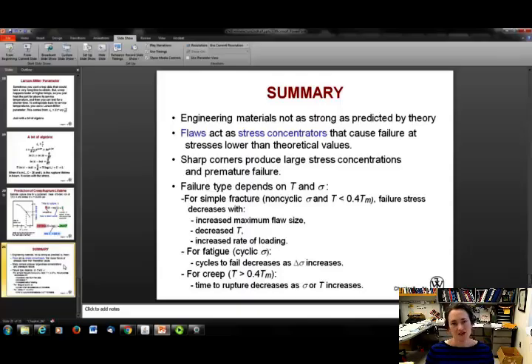In summary, engineering materials are not as strong as predicted by the theory that you might get from a tensile stress. Okay, they can fail at stresses much lower than their yield stress or their tensile stress. And the reason for that is, first of all, because materials are flawed. They have a lot of flaws in them, and those flaws, the scratches, the dings, the dents, or even just voids inside the part that might not be visible to the naked eye, they act as stress concentrators. And those stress concentrators can cause failure at stresses much lower than the theoretical values.